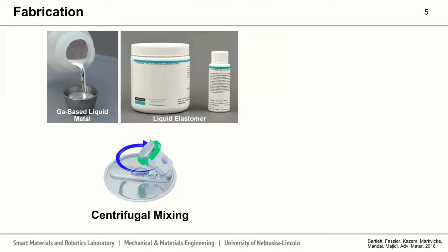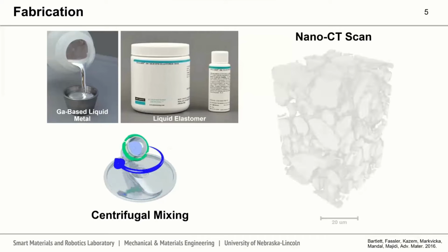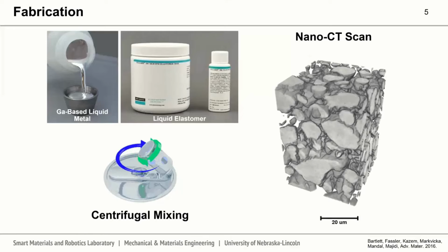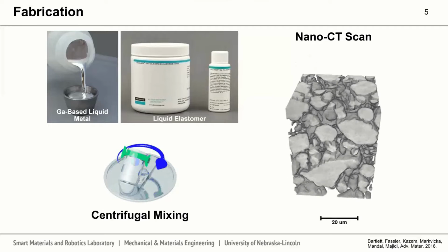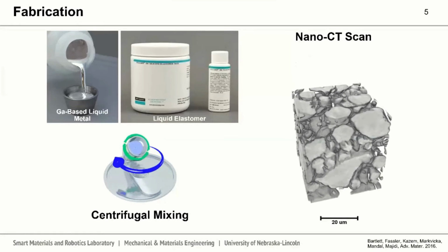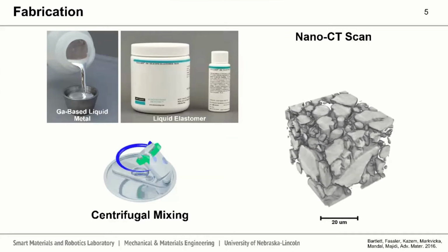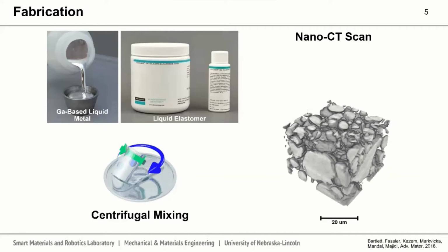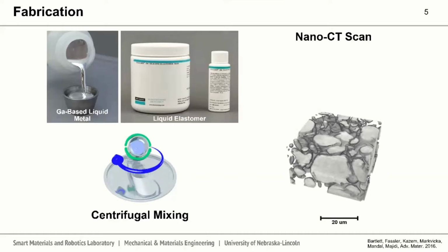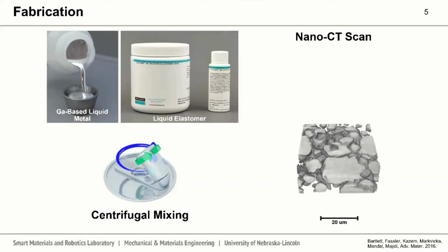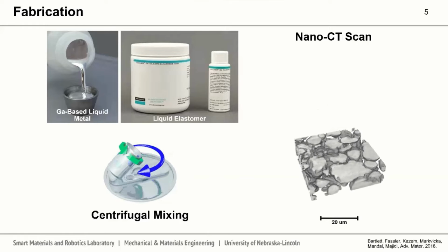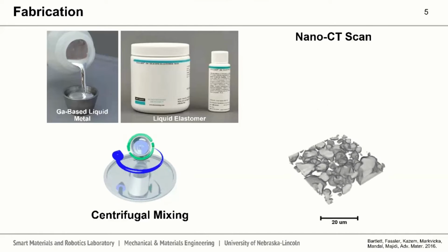We are focused on encapsulating this liquid metal into an elastomer composite, and we do this by mixing some volume ratio of the liquid metal plus elastomer. We combine this in a centrifugal mixer, and what we get out of this is this formation of droplets within the composite. They're independent droplets, as you can see in the nano CT scan on the right, as you have no droplet-droplet interaction. So even at very high volume loadings, up to 80% by volume, we are able to create composites that are electrically insulating.